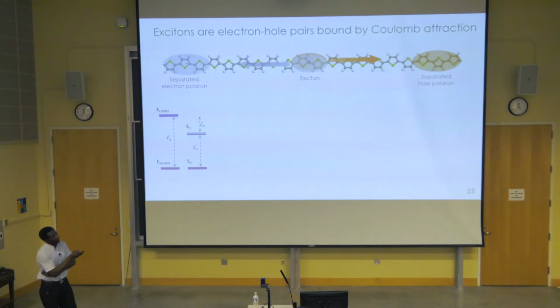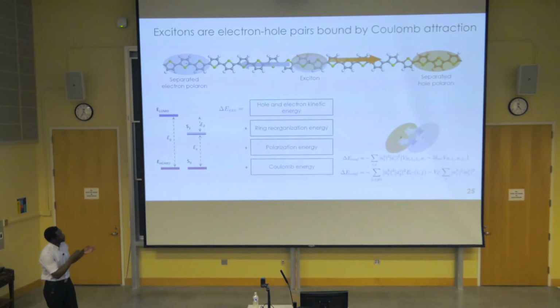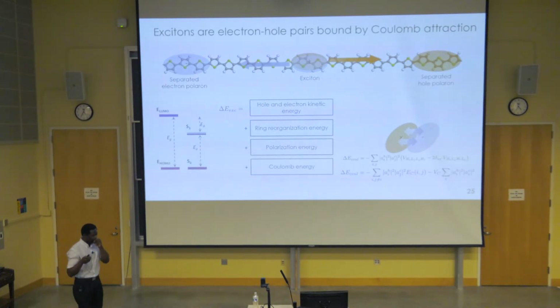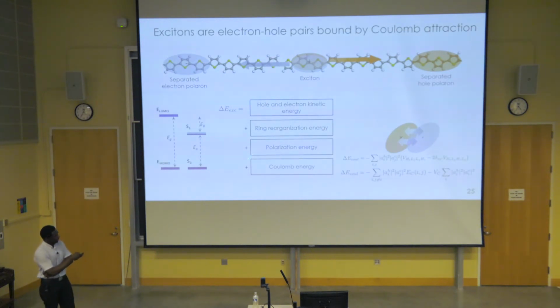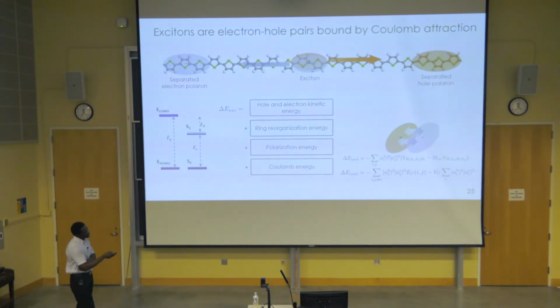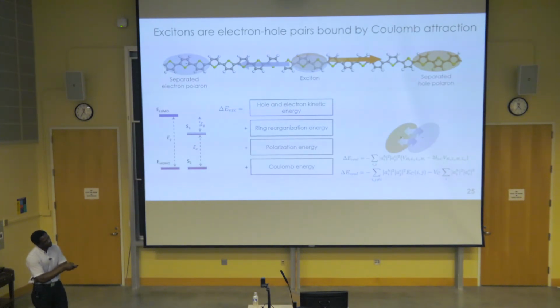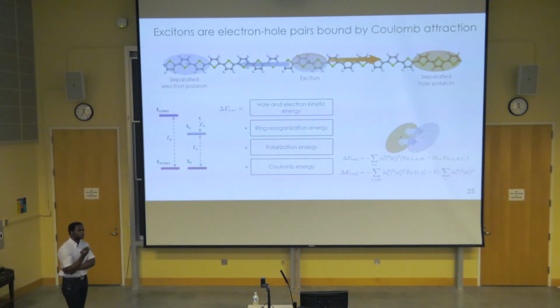And we've looked at the dielectric effect of the surroundings and the reorganization of nuclei. So to capture the energy of this process, we'll have the kinetic energy of the two charge carriers. We'll have the stabilizing effect that comes from the surrounding environment within the material, like ring reorganization and polarization energy. And we'll have the Coulomb attraction between the electron and the hole. And here, this equation, not to give you too much detail, just shows that we are able to represent the Coulomb attraction between the hole and the electron with just one additional parameter that needs to be computed using a first principle method.